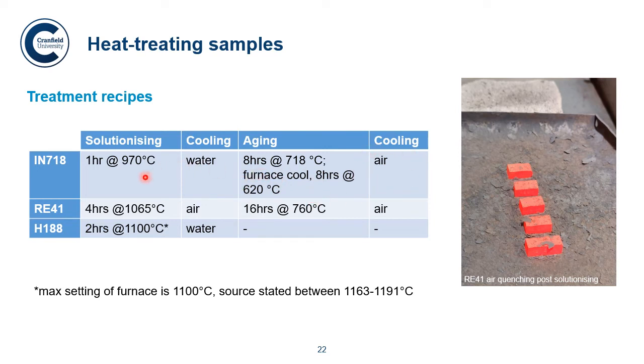Then Rene 41 underwent a solutionizing treatment of 4 hours at 1065 degrees Celsius, followed by air cooling, then a further 16 hours at 760 degrees, followed by air cooling again. And then Haynes 188, which is not an age hardenable alloy, just underwent 2 hours at 1100 degrees Celsius. And on the right you can see Rene 41 air quenching post its solutionizing treatment, which is a nice picture.